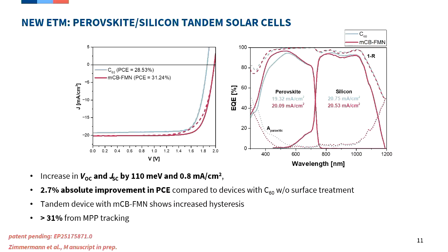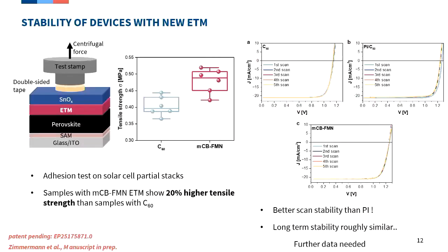Okay, so what about stability? We also measured stability, especially mechanical stability of the new molecule. We tried to measure the force needed to rip off that interface, and the new molecule, while not much higher, is at least a couple of 10% higher.